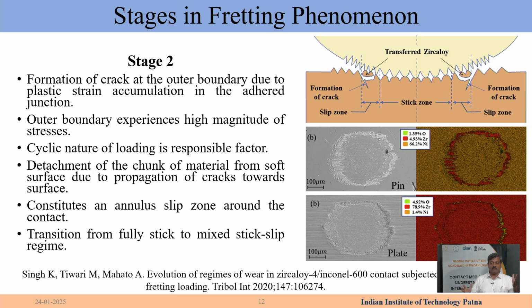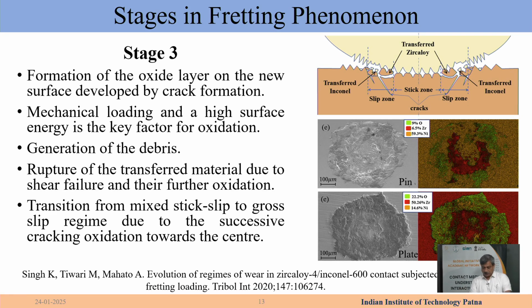And finally we see what we've learned in the last 4 days: it is completely gross sliding, where this circle is complete. You will see in the pictures, that's stage 3. Now there is a lot of oxide being formed. Generally oxides are hard, so they will create abrasion also, right. So mechanical loading and high surface energy are the key factors for oxidation. There's temperature there, right, so oxidation is happening. There is debris being generated, and the rupture of the transferred material due to shear failure and further oxidation.